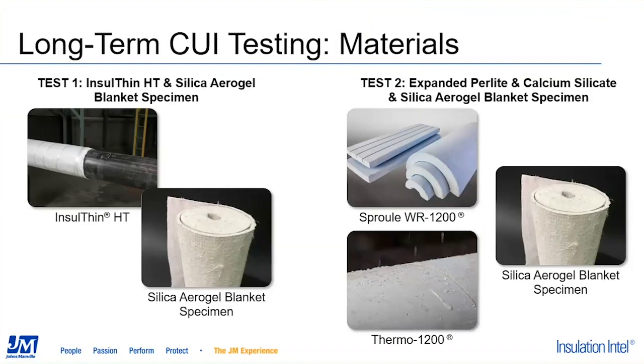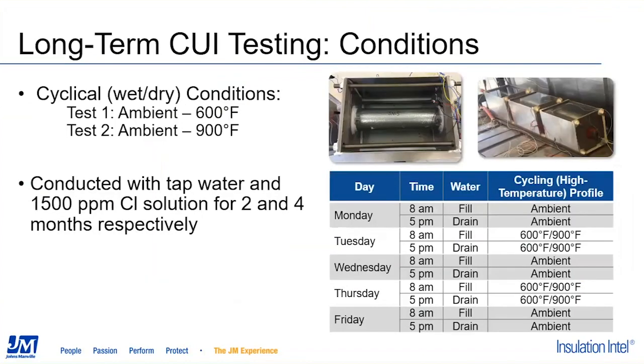So if we take a look at what we actually did with the test, we're going to focus on the pictures in the top right of the screen. Out of those two pictures, the one on the left is an overhead shot of the testing vat. And what you're going to see there is the actual pipe. It is insulated, and it's got the metal jacket on it. What you don't see is that on the underneath side, there's a hole drilled in that jacket. The purpose of the hole is to allow moisture and water to infiltrate the system. Make sure that you're seeing on the upper right-hand part of the screen the picture of the actual testing vats full of liquid.